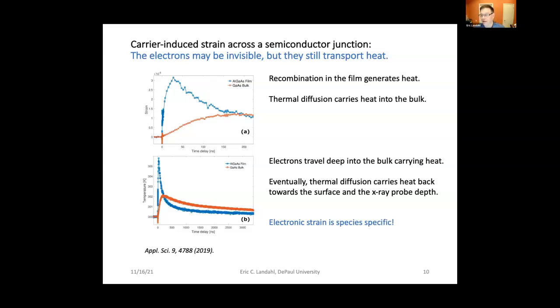So the deformation potential seems to pretty much fail for electrons. And so we conclude that the electrons must be somewhat invisible to a lot of the measurements that people are doing with diffraction. This is being followed up with several other measurements. We do know the electrons get there also because we can measure the voltage across the ends of our device and see what current actually travels. So electronic strain, or the deformation potential, appears to be species specific.